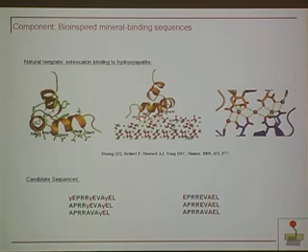So that's what you're seeing here, a geometric registration between the side chains on the carboxyglutamate residues and the calcium ions that are present in the hydroxyapatite lattice. And here at higher magnification is what the structure looks like. Our candidate sequences were from this N-terminal helix. The concept was to start with a sequence close to the native sequence, this sequence here, that contains 3 gamma E residues.